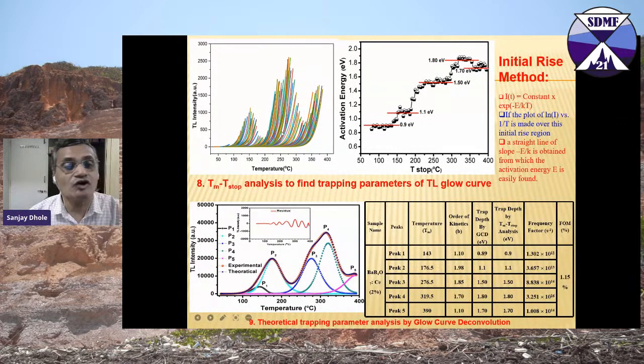So in TM-TStop, for a certain duration, say 2 minutes, then after 4 minutes or 6 minutes, you take the glow curve, and then you can plot TL intensity versus different temperature. There are many TL glow curves that have been taken, and then the TM-TStop was applied.